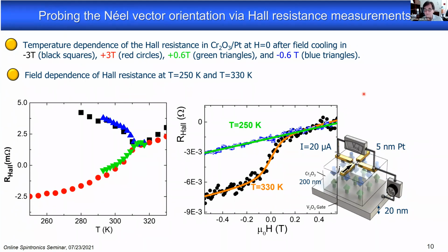What you do is you probe the boundary magnetization, which in turn is a direct fingerprint of the underlying antiferromagnetic order. And this is what we see here in our own system. When we prepare the system by applying a magnetic field on cooling and then heating up, we can select one domain state over the other. And if we do so, we can have the order parameter in one particular direction, and with that, the boundary magnetization in one particular direction.